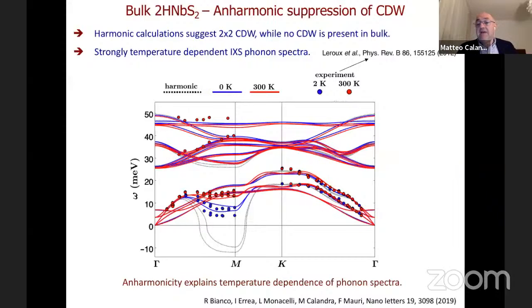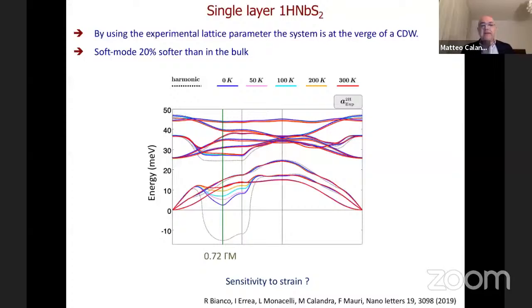And so at the time, we wrote that this would probably be due to anharmonicity, but we couldn't confirm it by calculation. And now in 2019, almost 7 years later, we took this problem up again and we did the full anharmonic calculation. As you can see, the temperature dependence turns out in very good agreement with the experiment for the low energy modes. And the instability that was found at the harmonic level is totally removed by anharmonicity. So anharmonicity stabilized the lattice in bulk niobium disulfide. Now, what happens in the single layer?